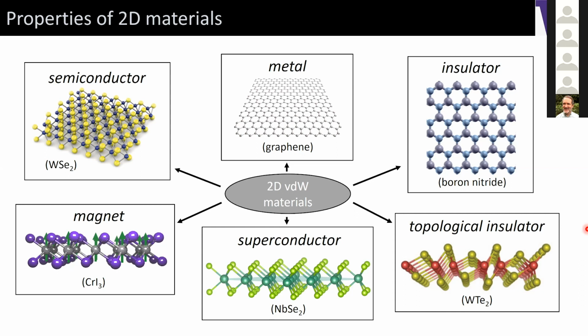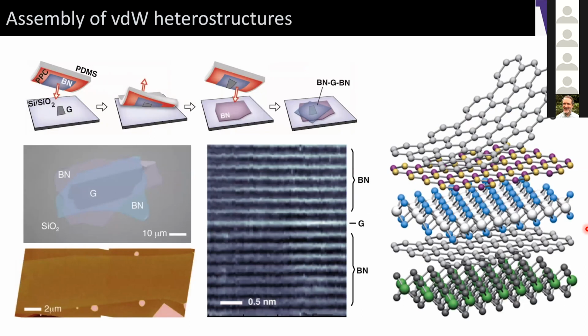But really the power of the field comes in the ability to take these isolated atomically thin materials and stack them together into a heterostructure. So this can be done by a dry transfer procedure that was developed at Columbia about a decade ago, where you simply pick the layers of these crystals up one by one and assemble them into a heterostructure that you desire. So here's just a simple heterostructure of graphene encapsulated between two flakes of boron nitride. If you take a cross-sectional TEM image, you can see the individual boron nitride and graphene layers. And of course, this is not something that you'd ever find in nature, but it's something that you can easily assemble in the lab. And really the phase space here is enormously large. You can basically make whatever heterostructure of these 2D materials that you desire.